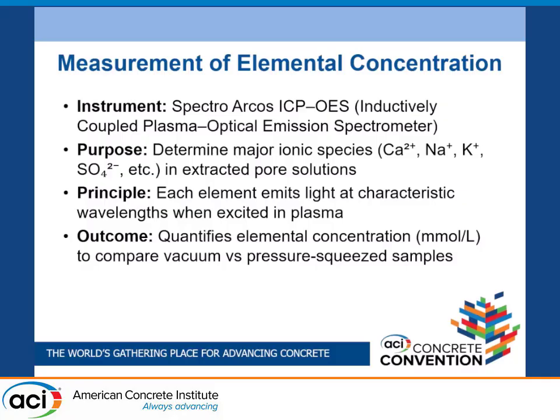We determine the major ionic species such as calcium, sodium, potassium, and sulfur. We also determine minor ions such as aluminum, iron, and magnesium, but they had relatively very low ionic concentration, so I'll not be discussing those ions in the results, because when analyzed, they only showed results below the detection limit.